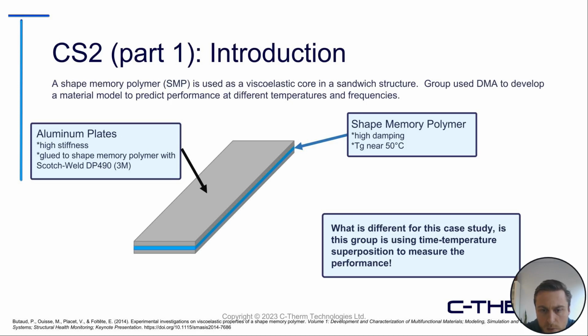They didn't state what the shape memory polymer was. They did state the composition, but didn't provide too much information on it. But it had high damping and a Tg, or glass transition temperature, near 50 degrees Celsius. The outer plates were aluminum plates, which have high stiffness, and were glued to the shape memory polymer with a Scotch-Weld DP490 from 3M.